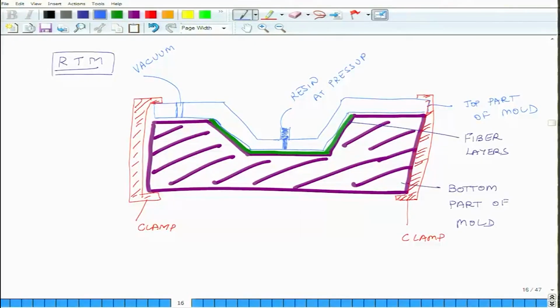but the pressure is not very high in the sense that when this resin flows through the fibers, it does not flow at very high velocity, it flows relatively slowly at modest pressures, and as a consequence the fibers do not get disoriented from their original configuration. And to ensure that, we make sure that whatever resins we use, they have low viscosity. So, you mix the resin with the hardener and you inject, and this resin with the hardener should have low viscosity, only then it will flow easily through all the network of fibers.